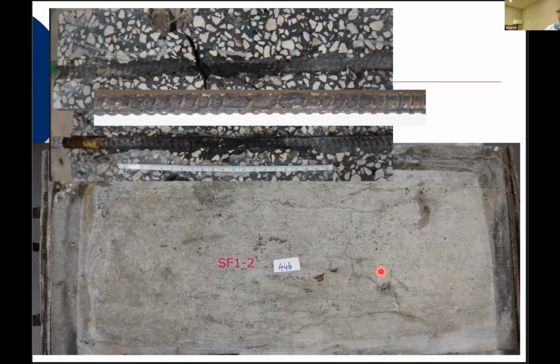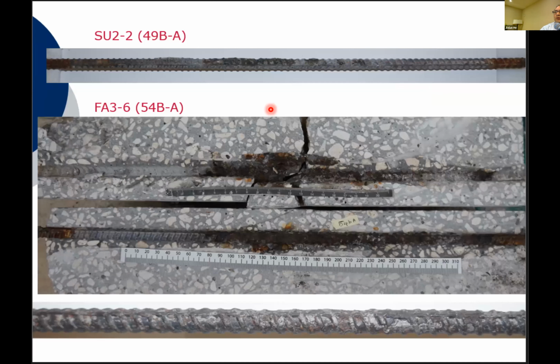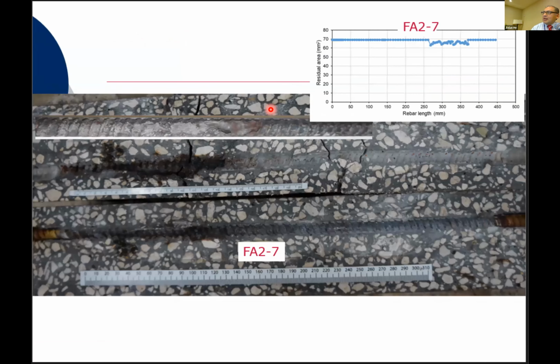So here are some images of the cracks that were observed on SF1, and the corrosion products right after we open it, and then what is the rebar surface after we clean it. I'm going to go through some of them, just a few additional situations. In this case, what we did, we used walnut shell to clean the rebars. And here is an example of the cross-section loss as a function of length.